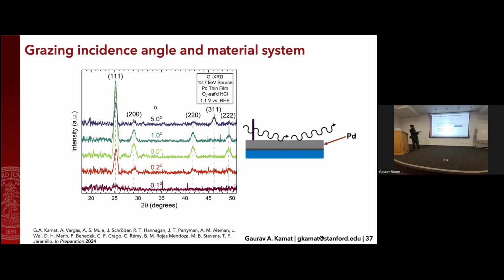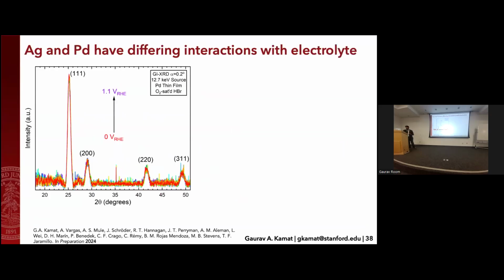But also, if we go to 0.1 degrees, your beam footprint is no longer as large. You're just not going to get enough signal from that. So 0.2 was sort of like the sweet spot that we chose for our measurements. And that turns out to a penetration depth of just a few nanometers. So we're measuring the crystallinity in just the topmost few nanometers of our sample. And this is what some of that data looks like.